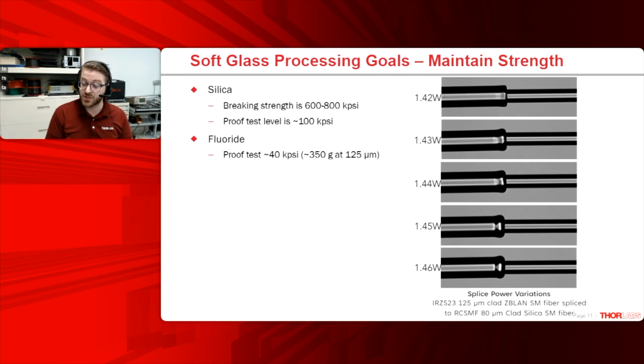The change in strength across these is incredible, though. On the cold and hot end, on the top and bottom here, these each had a splice strength of around 50 grams, whereas this middle one, the Goldilocks, had a splice strength of over 200 grams. So a lot easier to measure, a lot easier to set as a goal.